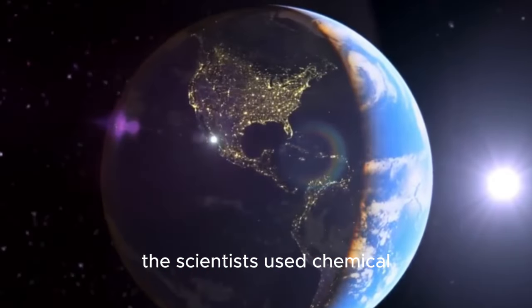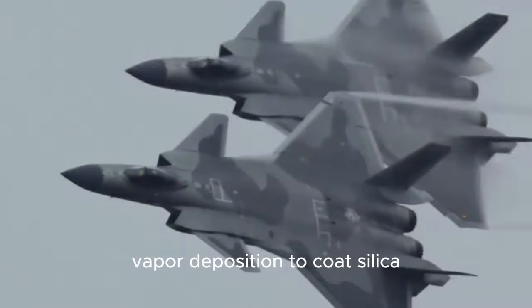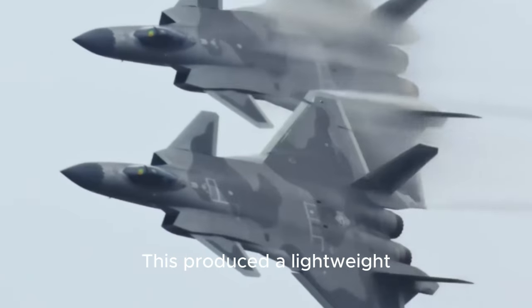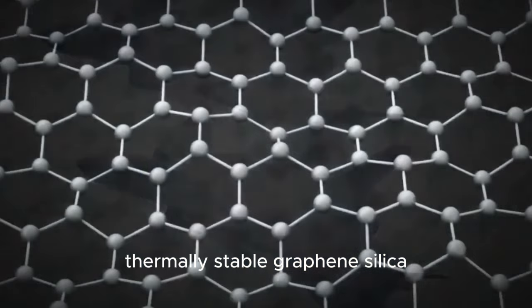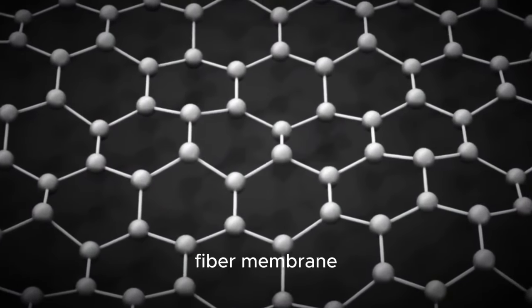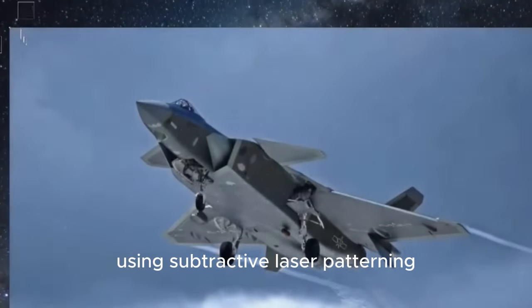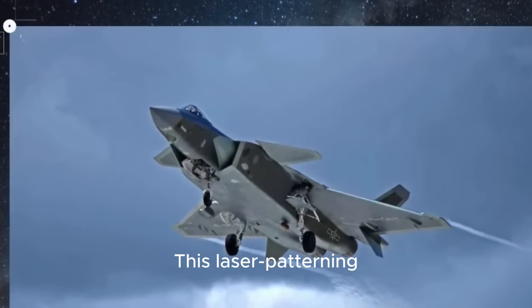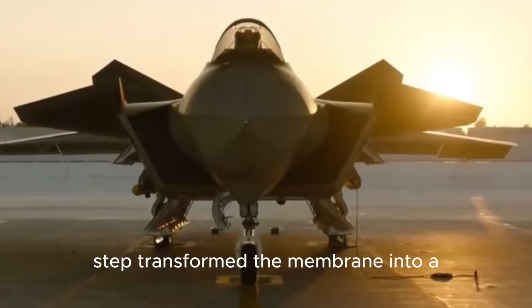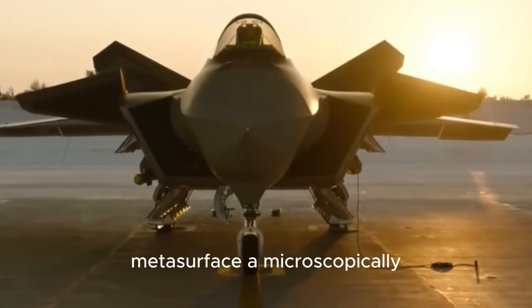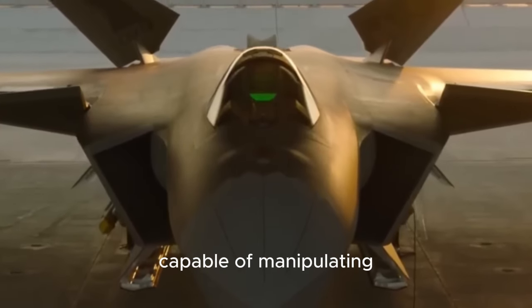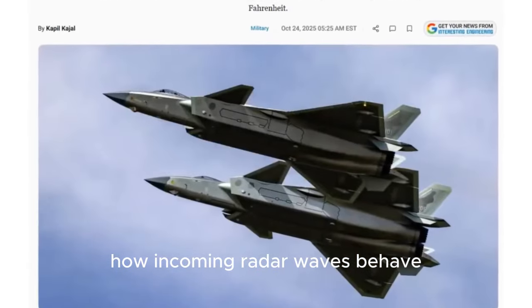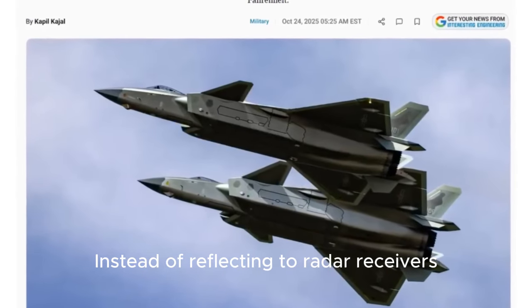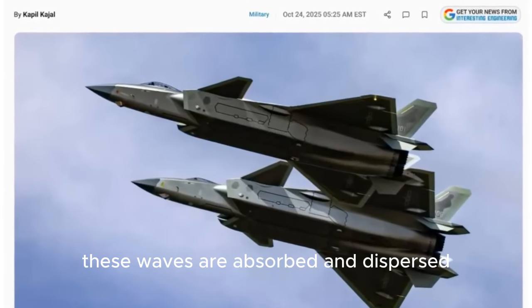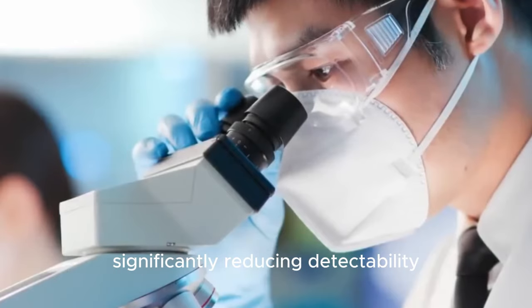radar-absorbent materials ever reported. To build this material, the scientists used chemical vapor deposition to coat silica fibers with graphene. This produced a lightweight, thermally stable graphene silica fiber membrane, which they later refined using subtractive laser patterning. This laser patterning step transformed the membrane into a metasurface, a microscopically structured layer capable of manipulating how incoming radar waves behave. Instead of reflecting to radar receivers, these waves are absorbed and dispersed, significantly reducing detectability.